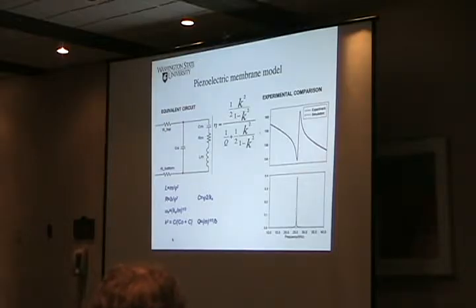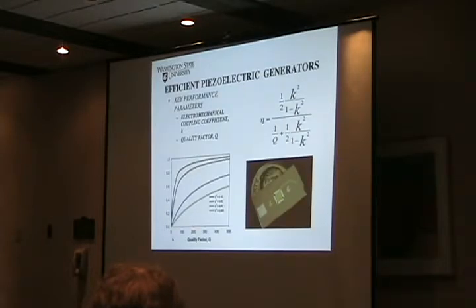So, piezoelectric cavities, we have an equivalent circuit model that'll let us back out things like coupling coefficient and Q. For the way we assemble these in an engine, our old DARPA program manager used to do MEMS and say, well, we'd be out here somewhere. Well, unfortunately, with all that fluid back there, we're somewhere around here. So what becomes important is the electromechanical coupling coefficient of the device. Our Q is not going to vary much between about 20 and 50, and so we're stuck trying to make higher K squared values rather than push our Q values up.